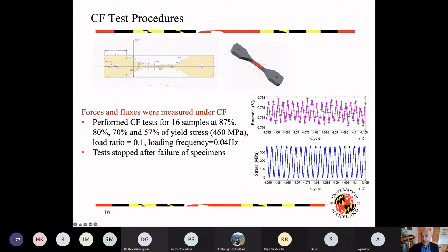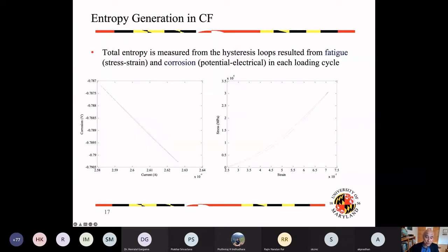So as I said, the hysteresis loop inside each of these shows the amount of corrosion damage, and the area inside here shows essentially the strain energies which are dissipated. And the sum of the two. Note here that both of these translate to the same measure of entropy, okay? And they can be summed very easily. The cumulative amount of the two damages can be summed as I'm showing here. So this shows the hysteresis loop of the corrosion. This shows the corrosion voltage measured. This shows the current. You can see the area inside the graph is very tiny, but that is how much energy is dissipated.